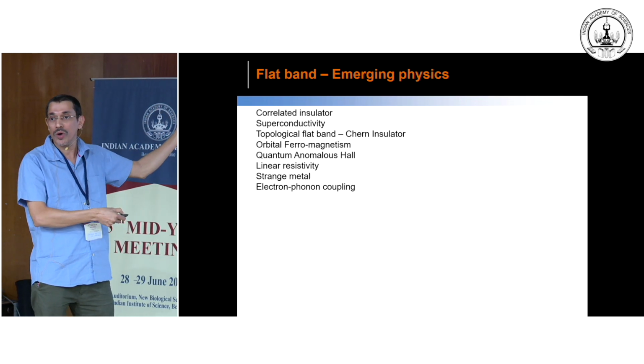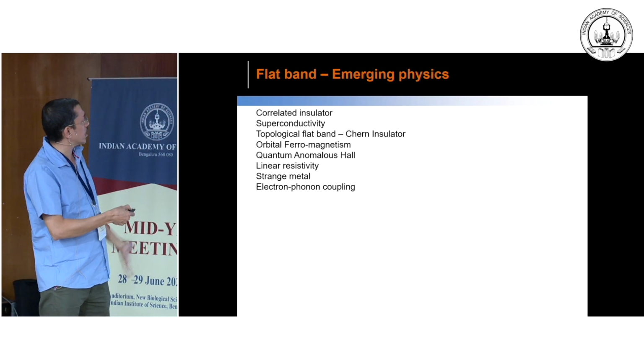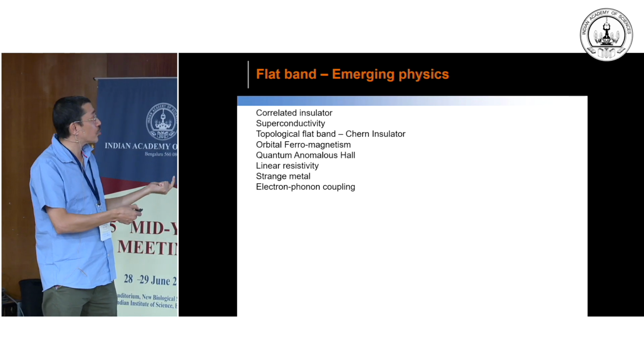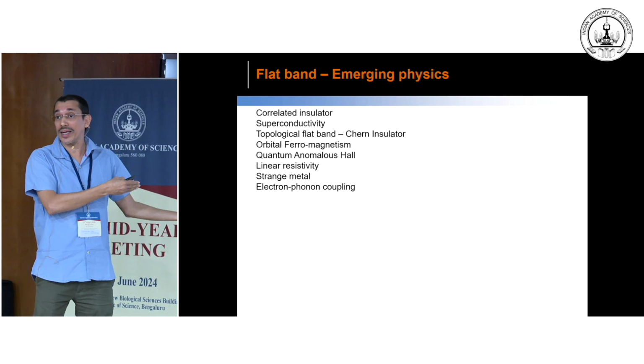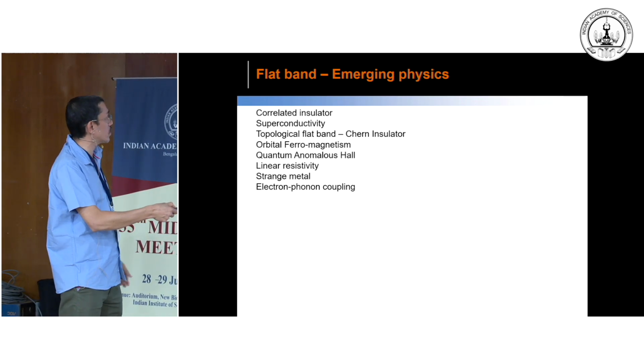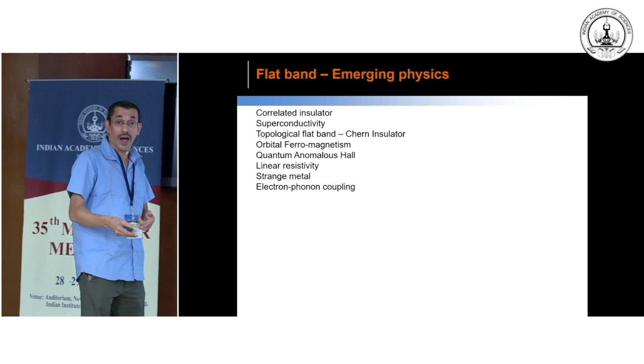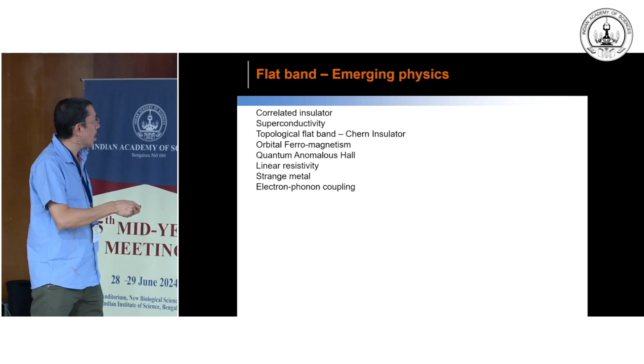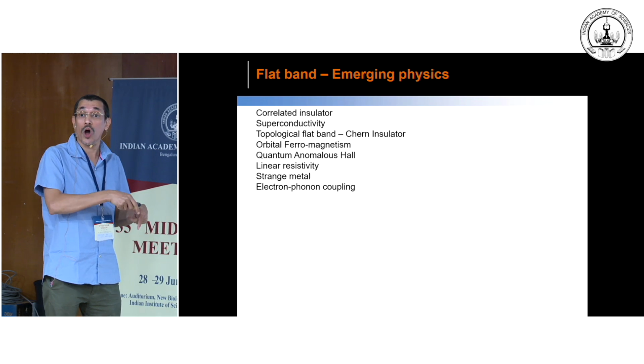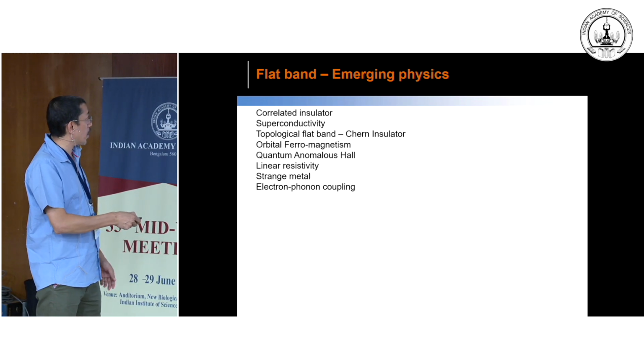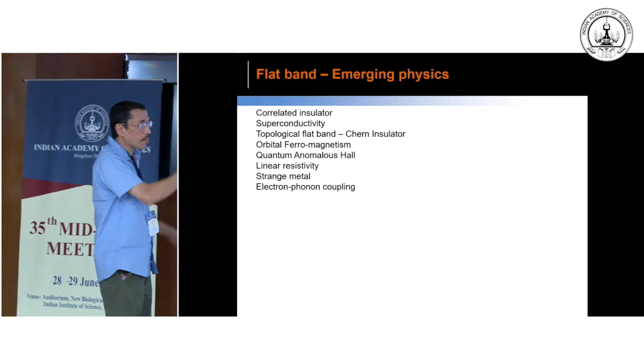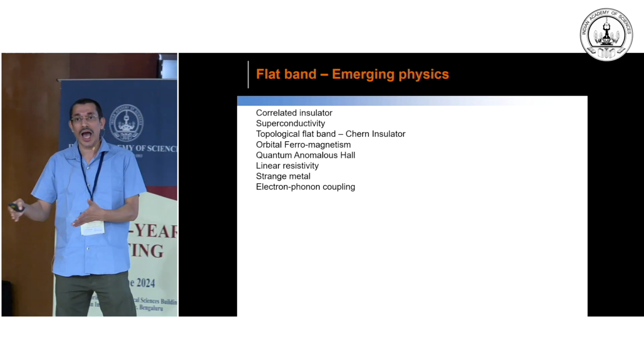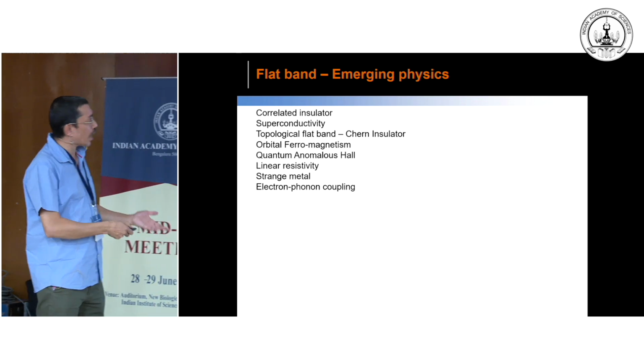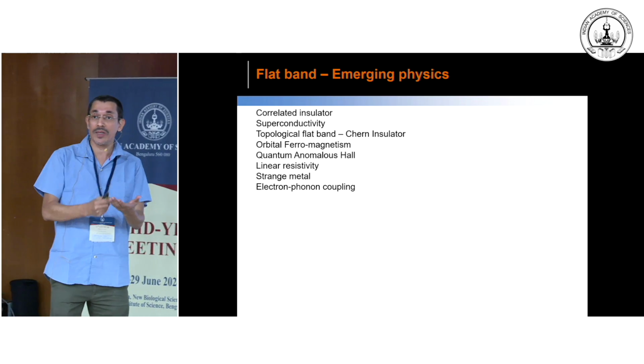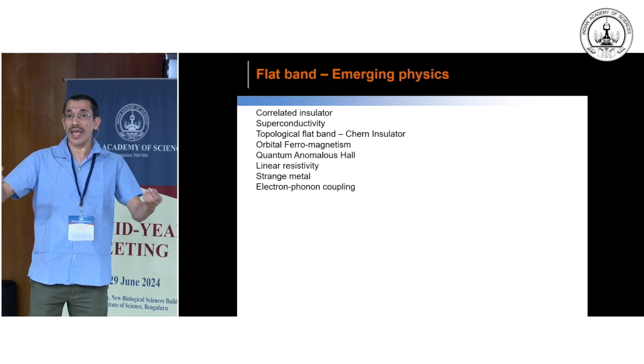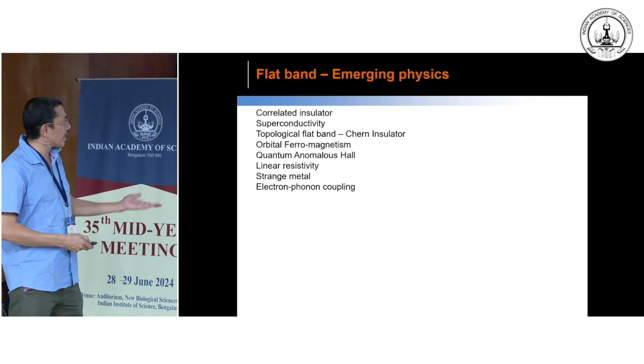On the same platform, you can have many interesting physics, the idea I was talking about. For example, superconductivity, topological insulator, Chern insulator, which is like quantum Hall physics at zero magnetic field, and even fractional Chern insulator physics. There has been orbital ferromagnetism, again coming from the Berry curvature, quantum anomalous Hall, linear resistivity down to the T tends to 0 limit, strange metal, and large electron phonon coupling. So many of these exotic things that you would like to have on a condensed matter platform, you can have in twisted bilayer graphene, where you can change the twist angle, the carrier concentration, temperature, magnetic field, and so on.